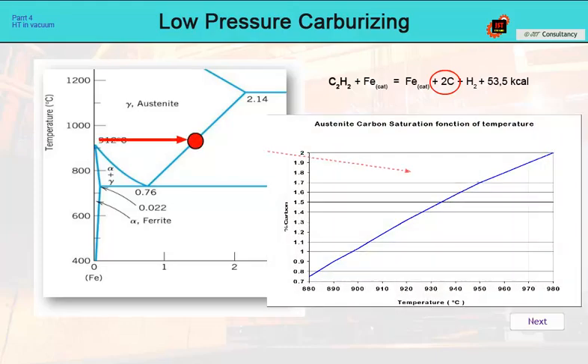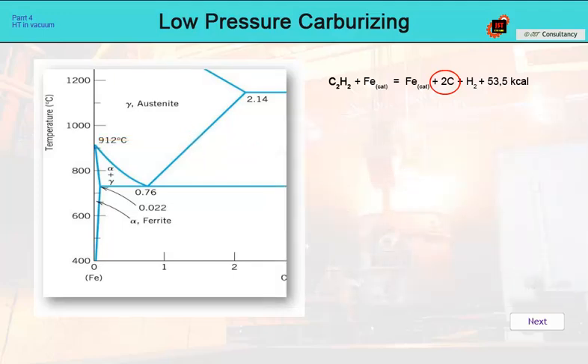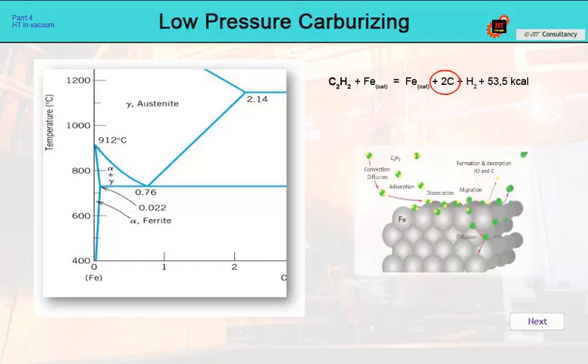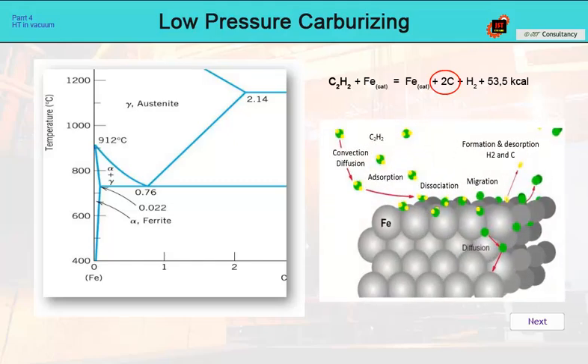The carbon from the saturated austenite travels further from the surface of the steel to the core. It travels from places where the carbon content is higher to places where there is less of it. Since the diffusion rate is dependent on the concentration gradient, in the first stage the carburizing rate is high. However, it gradually slows down as the carbon progresses deeper.